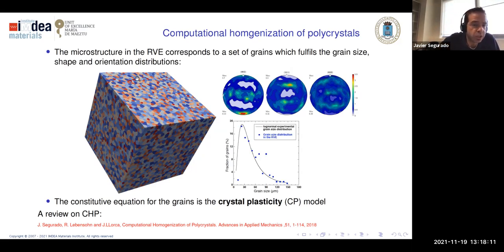In terms of the microstructure, if we want to study a polycrystal, what we need is the distribution of grain size, shapes, and orientation. In this picture, what you have here are the pole figures. That's telling me the texture, so this is the orientation distribution. We can get it from EBSD or from any type of diffraction technique. What you have here in the graph is the grain size distribution. In this case, it's a log normal, and we can also get it from experimental images. It tells which is the distribution of grain sizes.